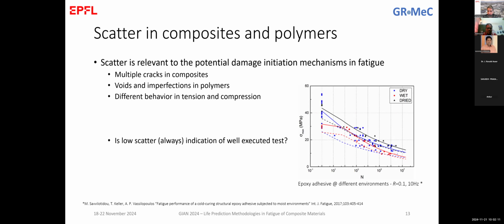So the statistical significance of a data set can be examined by tools that we have in statistics. You have goodness of fit tests that you can apply to your distribution and see if your data is statistically valid. For example, in your question, if you fit a distribution to this data set, then there is a second test that you can do, which we call a goodness of fit test. It shows if the statistical distribution that you are fitting fits your fatigue data well. And if it fits your fatigue data well, it means that you have a data pool, a sample, that is statistically correct.